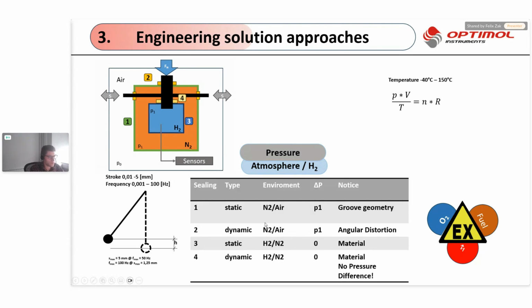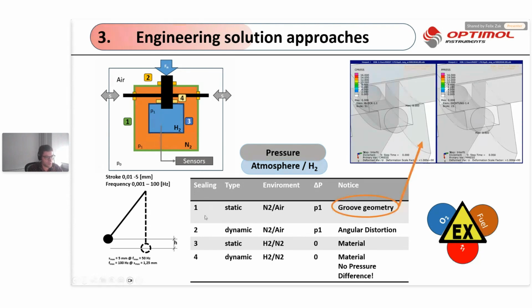Here on that table, you see the different sealing types. So first, number one, the static one here, which separates the nitrogen and the air part, is very sensitive to the groove geometry. Here you see a small video of how such a sealing acts. First, we have a compression due to the mechanical stress, and then when we apply a pressure, you see the second deformation, which increases the contact area, which will lead to a sealed system.